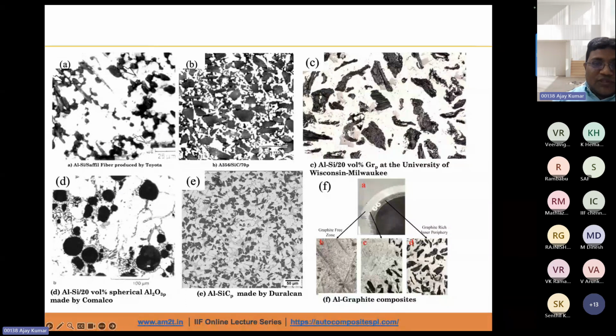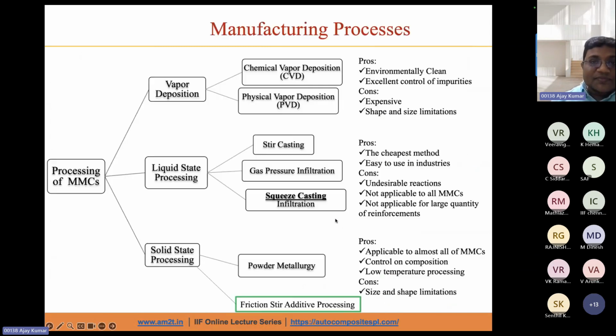metal matrix composites. So these are the real pictures, real microstructures where we have seen aluminum silicon alloy reinforced with Saffil fiber, and then aluminum alloy with SiC reinforcement of different volume percentage. So you can see here the size of the reinforcement also is varying, and the volume percent also is varying. And then this is the microstructure for aluminum graphite composites. So these composite materials can be used for tribological applications where you need less friction and more wear resistance.